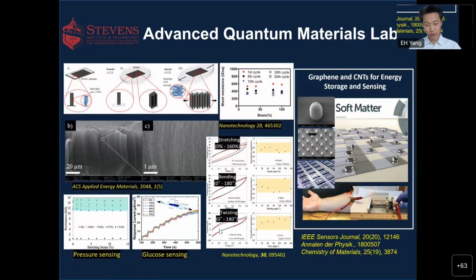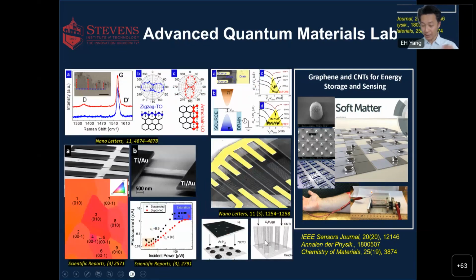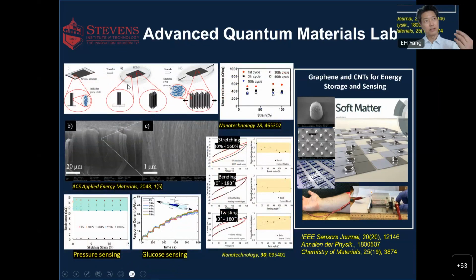We also grow carbon nanotubes for supercapacitor applications. We also combine these carbon nanotubes with flexible substrates, in this case half-cured PDMS. We put these carbon nanotube carpets onto the half-cured PDMS, and then you cure. Then individual nanotube roots are tightly bound to the PDMS. They become firmly attached. As you can see with this arrow here, when you stretch this PDMS substrate, the carbon nanotube carpets move along with the substrate, so they don't lose their integrity.